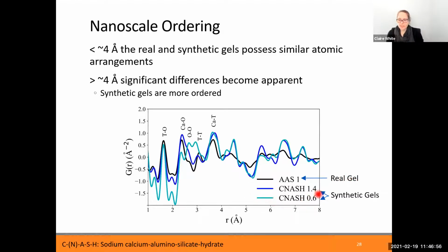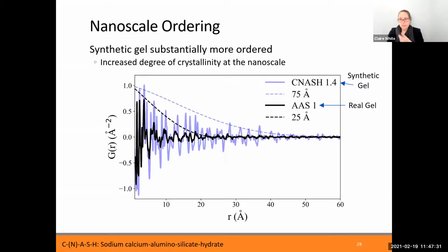And then we've plotted 2 of the synthetic gels with different starting calcium to silicon ratios. And so especially if you compare the dark blue and the black, you see they're kind of similar up until about 4 angstroms. The light blue is a little bit different because it's got a different overall composition for the gel. But then what you can see is beyond about 4 angstroms, it's actually the 2 blues that become more similar. And then the black itself, which is the real gel, is a lot less intense. And so if we quantify how quickly the atom-atom correlations drop off as you look at increasing distances, we see for the synthetic gel, and this one's shown in purple, that the envelope in which it drops off is a lot slower in distance compared to the black curve.